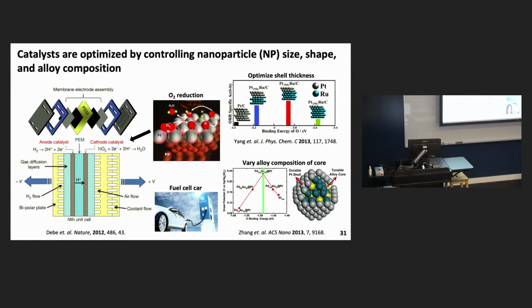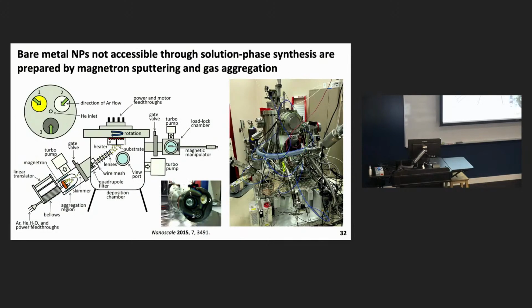less expensive. So on the right-hand side, I have some results from the literature where theoreticians have gone in and calculated various arrangements of atoms that would give you the ideal oxygen reduction potential for this important process. And on the top, you can see they think 2 layers of platinum on ruthenium is ideal, and then down here they think in this core shell species that something with this stoichiometry would give you the ideal reduction potential. And that's very helpful, but the issue is how do you make these things, right? There's not really a clear way to do that in solution because metals have different reduction potentials, and when you reduce them, you end up with a clump of one metal stuck to a clump of another in a lot of cases, right? So we thought we had maybe a unique way to try and address this problem,